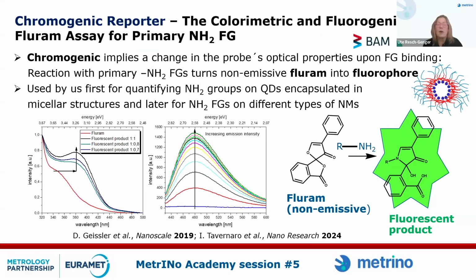Then there are other ways of using functional group assays. A very common assay is the so-called fluorescamine assay, where you have this dye, which is non-colored, non-emissive, and this dye selectively reacts with primary amino functionalities, forming absorbing and fluorescent products. It was first developed for protein analysis. A lot of these assays have been developed for measuring functional groups on proteins. That's the reason why they're available for amino groups, thiol groups, or carboxylic acid groups.